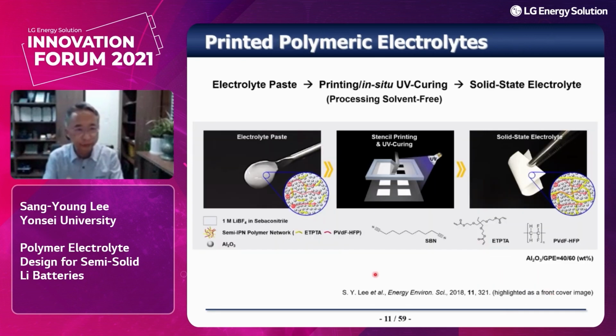Then let me show you how to fabricate our electrolyte. We started with the electrolyte paste like this. The electrolyte paste is composed of the sebaconitrile-based organic electrolyte, the polymer, the UV-curable monomer, and alumina. This electrolyte paste was printed using the stencil printing technique like this, followed by in situ UV curing. The more important point is that throughout the whole process, we do not use any processing solvents such as acetone or NMP. Eventually we have obtained the solid-state electrolyte like this.